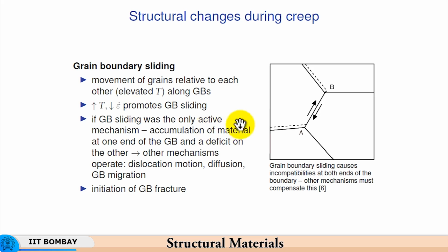On the other hand, if strain rate is higher, then you have viscous strengthening taking place at the grain boundaries, due to which you will not have so much grain boundary sliding taking place, because the forces are countered by an increase in the local strain rate of grain boundary sliding, and the viscous effects will essentially increase the strength at the grain boundary. So, when the strain rates are relatively low, it promotes grain boundary sliding, because the grain boundaries remain relatively weak as compared to the interior of the grain, and that is also supported by an increase in temperature. So, diffusion and weakening of the grain boundary both are supported by increase in temperature.